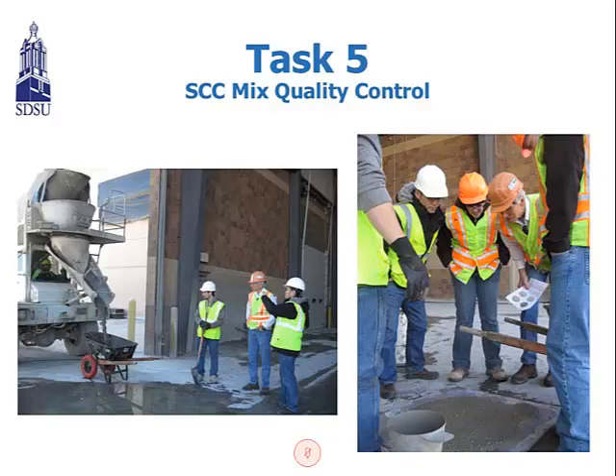And before pouring the SCC concrete, we conducted quality control with the Wisconsin DOT technical panel, me and the grad student. We evaluated mixture number 4 again with the J-ring, the slump flow and the column segregation, and the chief of the Wisconsin DOT material panel investigated the VSI. I remember we conducted the SCC mixture quality control twice or three times before we poured the concrete in the form. So here's the picture, after completing the slump flow test of mixture 4, before fabricating the concrete girder.